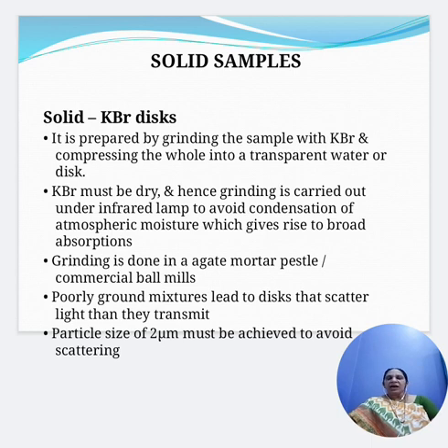The next one is your solid samples. Solid samples are made into potassium bromide discs. It is prepared by grinding the sample with potassium bromide and compressing the whole into a transparent wafer or disc.